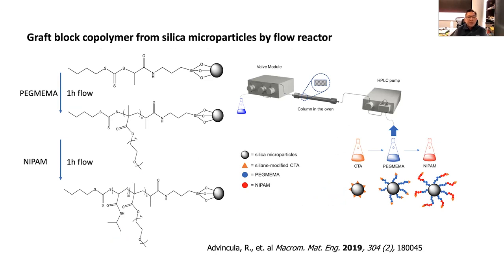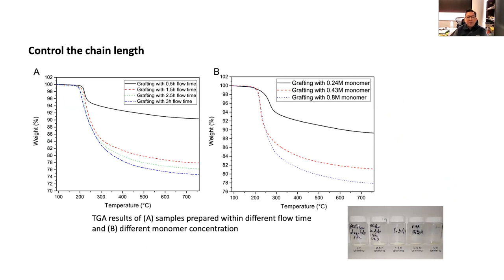On the other hand, as I've shown earlier in the schematic diagram, we can then switch from one monomer to the next. So the first monomer that was introduced was based on the PEG methacrylate monomer. After washing any excess, we then introduced the N-isopropyl acrylamide monomer, so that the end result, as shown here, is a block copolymer or a diblock that is attached to the surface. And we prove this by looking at the thermogravimetric analysis, which shows the grafting of the monomer